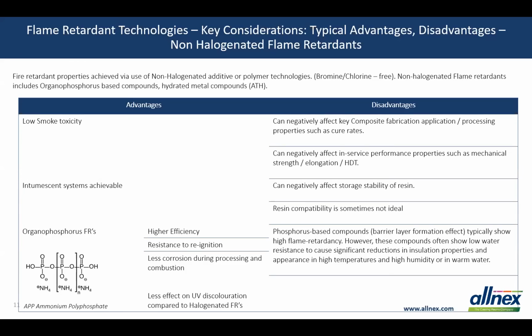Some negative effects, however, on resin application, and it does depend on the additive. As I said, there's a lot of different types of technologies among non-halogenated flame retardants, but a lot of them do have negative effects on resin application properties, such as cure. Also, they can affect physical and mechanical properties, some, not all. So it's also always a challenge to balance these properties. Other resin performance properties can be more commonly encountered with the use of these materials. So they present a challenge sometimes to the resin development chemist in formulating suitable resins for fire retardant applications with these and getting around these problems by utilising other materials to overcome those sorts of deficiencies. Very common examples of well-established non-halogenated flame retardants include APP, or ammonium polyphosphate, and alumina trihydrate, as mentioned, which we've used for many years. Many different applications.